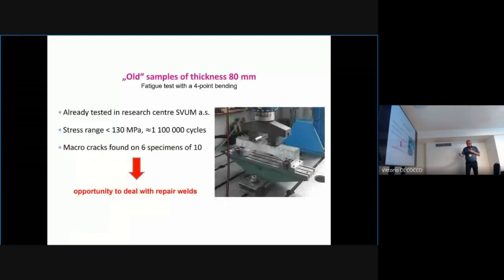Then we obtained samples with the name old of a thickness 80 millimeters. They were tested before we obtained the test specimens at a stress range which was lower than in the former example, to approximately 1 million cycles. And we found by non-destructive testing macro cracks on 6 specimens of 10, and it was an opportunity to deal with repair welds on this type of welds of plates of high thickness.